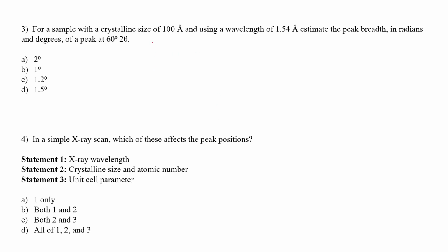So basically there is one Scherrer formula which relates the crystal size to the peak width of your X-ray diffraction studies, which is given by the beta, which I wrote down. I guess I have discarded that ink, which is given by this beta. There is one Scherrer formula which relates your crystal size, how thick your specimens are. So it is given by beta is equal to lambda divided by your crystal size, I'm just writing it as S, into cos theta.